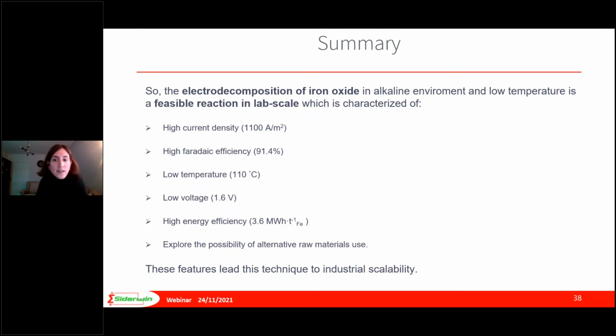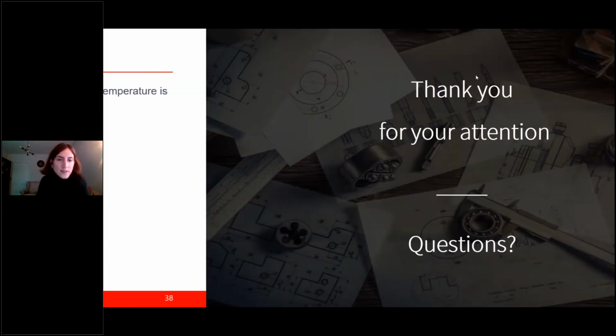Of course, the electrodecomposition of iron oxide in an alkaline environment at low temperature is a feasible reaction at lab scale, which is characterized by high current density at 1100 amperes per square meter, high Faraday efficiency 91.4%, low temperature 110 degrees Celsius, low voltage 1.6 volts, and high energy efficiency 3.6 megawatt hours per ton of iron produced, and has the possibility of alternative material use. All these features lead this technique to industrial scalability. Thank you very much.